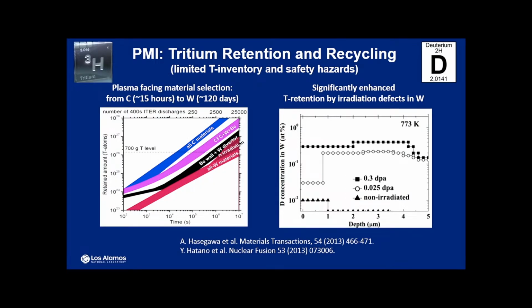ITER was designed in the beginning with carbon as the plasma-facing material. Then we very quickly realized that if you use carbon, the tritium is going to form methane and be trapped into the carbon very quickly. Depending on how many shots, this is for the number of 400-second ITER discharges, and the retention of tritium, this is the safety limit here: 700 grams in the material. You can only do 15 hours with a carbon wall. You probably can't do many experiments. So they quickly changed it to tungsten.